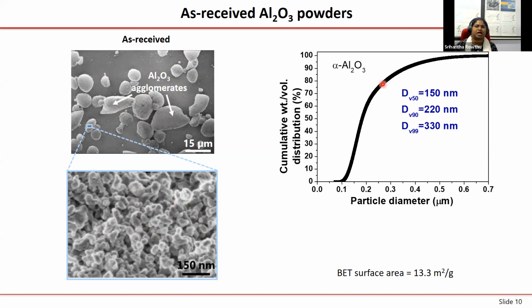In principle, we have also characterized the particle sizes after de-agglomerating these powders, and here we can see that D50 is 150 nanometers, D90 is 220, and D99 is 330. What this means is that D50 means 50% of the particles have a size less than or equal to 150 nanometers. Similarly, 90% of the particles have a size less than or equal to 220 nanometers. In that way, you can interpret it. Of course, it's a distribution. It's never a single value when you are looking at particle sizes. So predominantly the sizes are around or less than 200 nanometers or so.